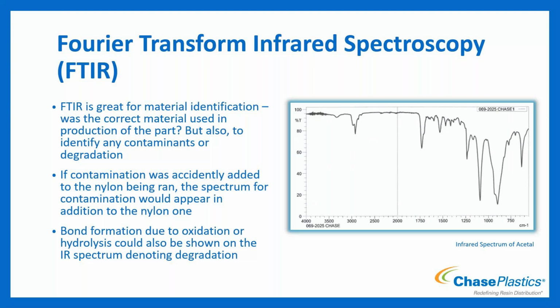The other thing that you'll note too is the two examples that I gave currently, they're done by percent transmission. That's why you have the percent T. Sometimes, or if you get them from other places, you'll see it's done by absorbance versus transmission. And so if it's 100% or near 100% transmission, nothing's being absorbed by the polymer. It's going right through it. And then on the sections where you see the peaks, down on this particular one, you can see them at 3,000, a really big one at, we'll call it 800 for the acetal. That's not very transparent in that area because the acetal is absorbing it because of those bonds.